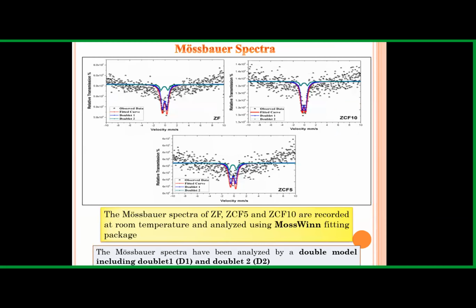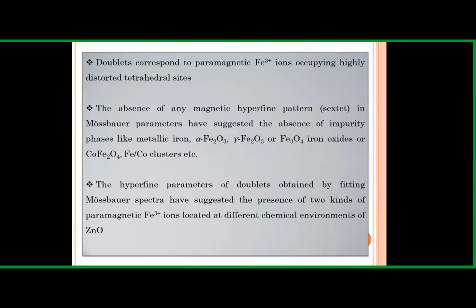Then we used the Mössbauer spectra to identify the presence of iron in our samples. The Mössbauer spectra also show a doublet, which was then fitted using software, and cobalt and cobalt iron doped nanoparticles.